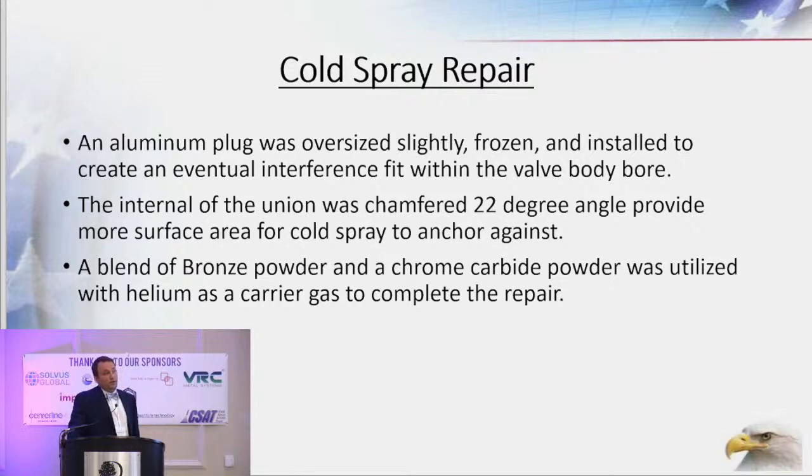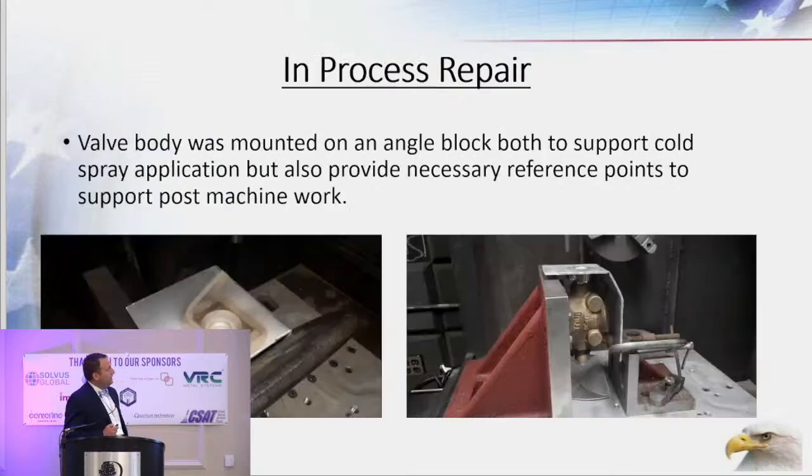So we reached out to ARL and said, hey, we're trying to spray this powder. Ideally we'd like to do it with nitrogen. They were doing it with nitrogen. They said, hey, we're having a lot of issues with delamination, probably the lead content in the bronze. They recommended going with helium, since it'll keep it cooler. So that's what we ended up doing.